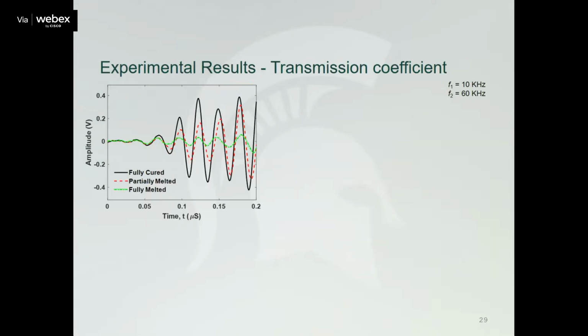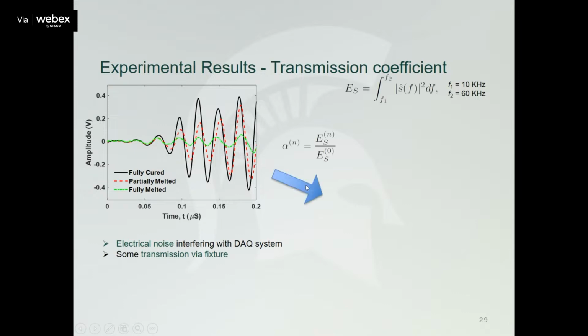This tells you the experimental results. Comparing to the transmission coefficient you are getting in the simulation, we can use the same approach to calculate this transmission coefficient. But one thing you notice in the experiments is that you have electronic noise interfering with the DAQ system, and even for fully melted, you still have some energy transmitted through, right? So this is something you have to deal with in the experiments. In simulation, it's going to be exactly zero.